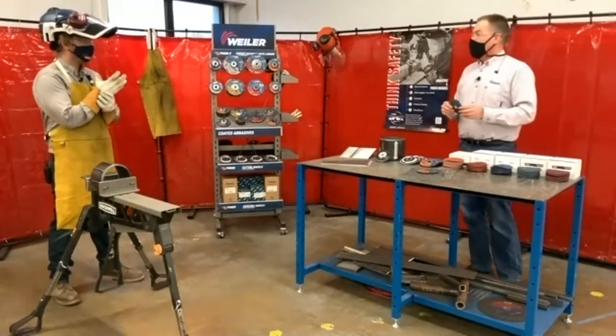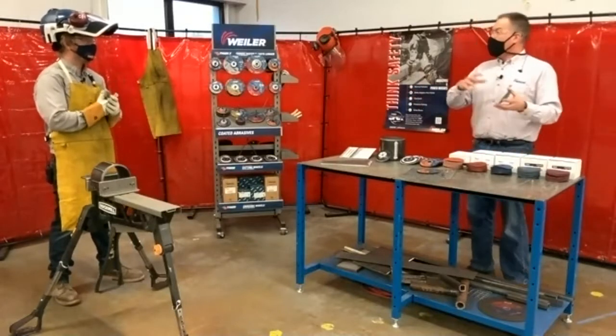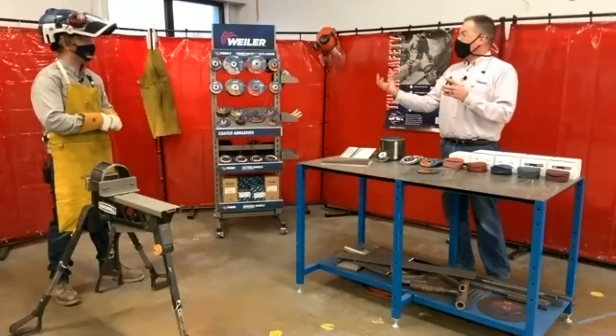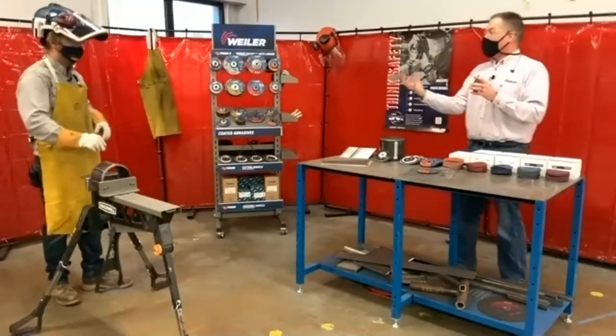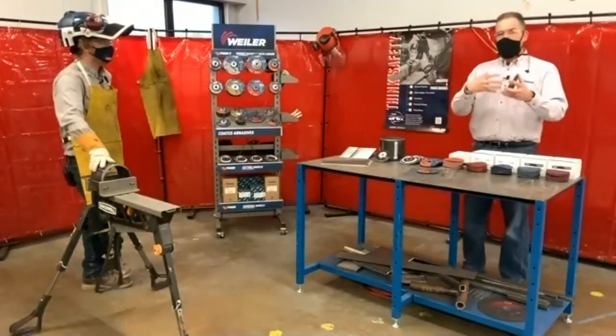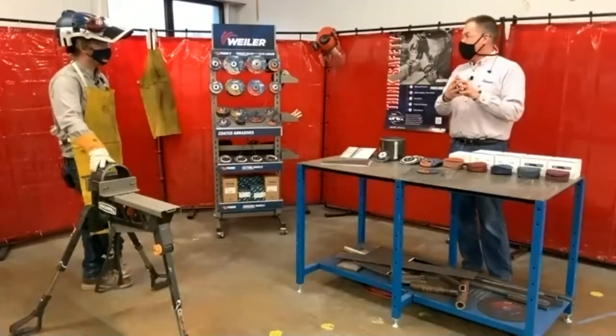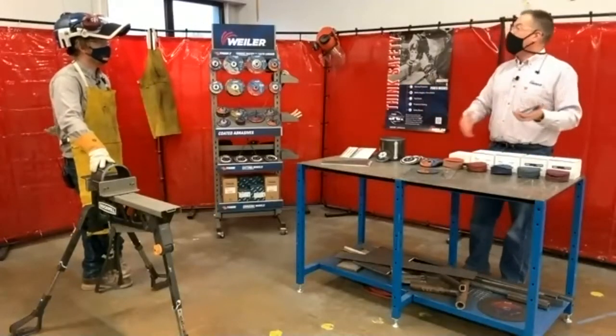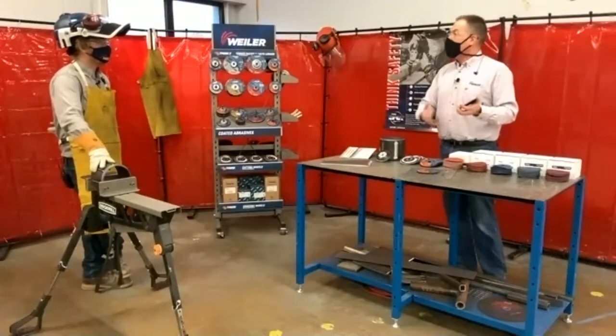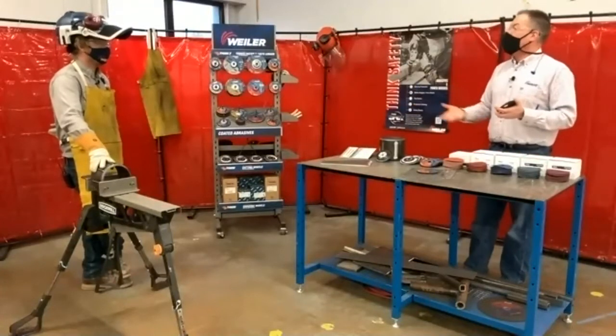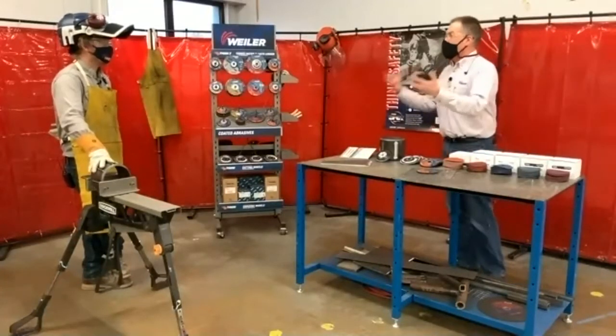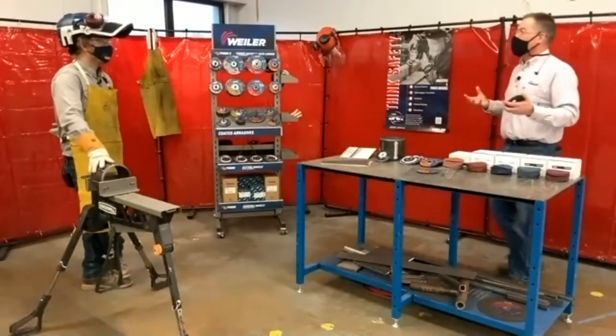Wolverine Zirc is really a great product in that it provides a lot of the benefit of the zirconia alumina grains that we just talked about. But by incorporating aluminum oxide into the mix, now you do have a product that can give you some of that better finish quality and finish pattern right at the tail end, without having to change or switch the disc to an aluminum oxide.